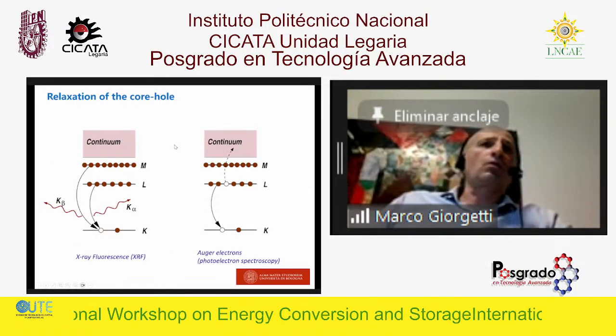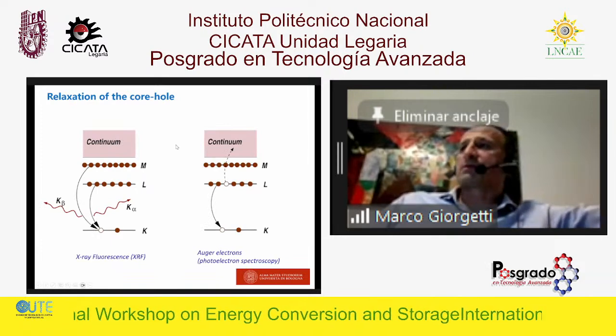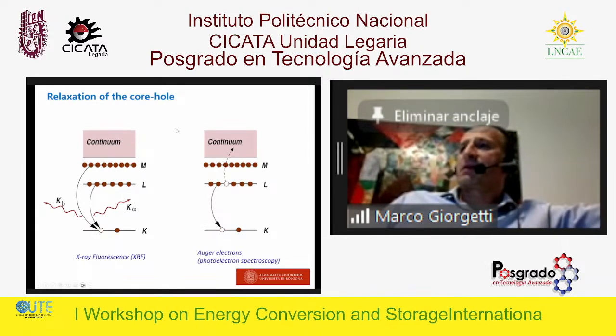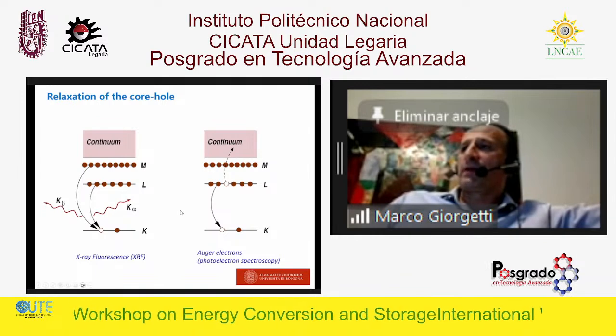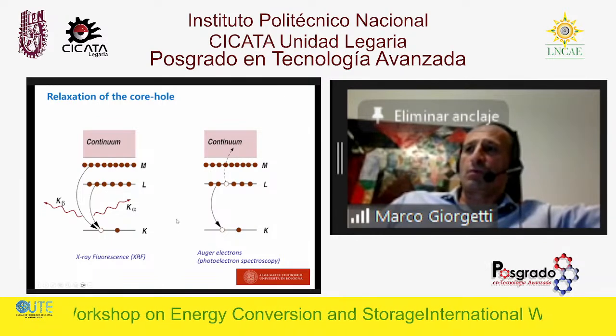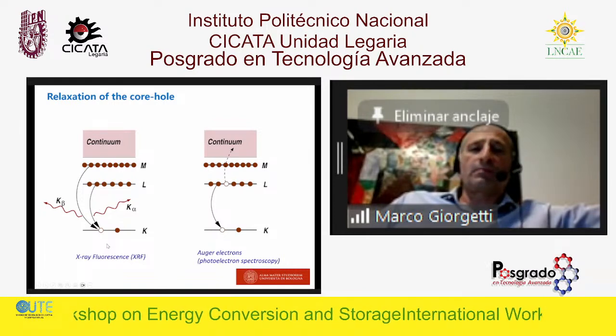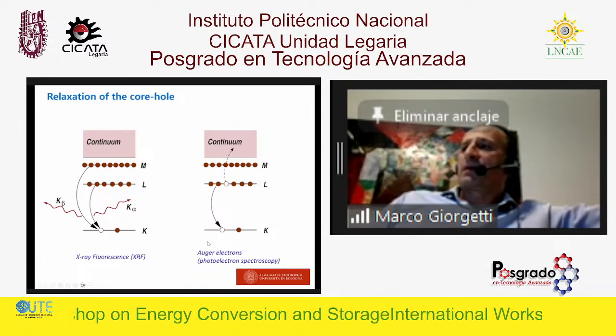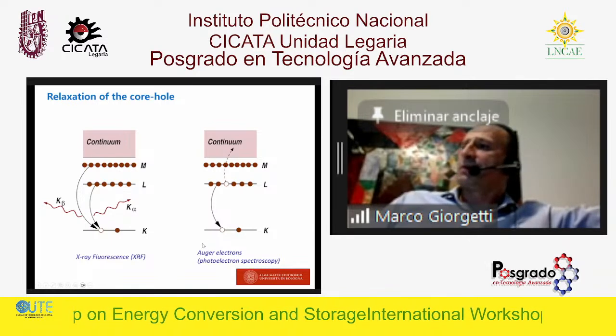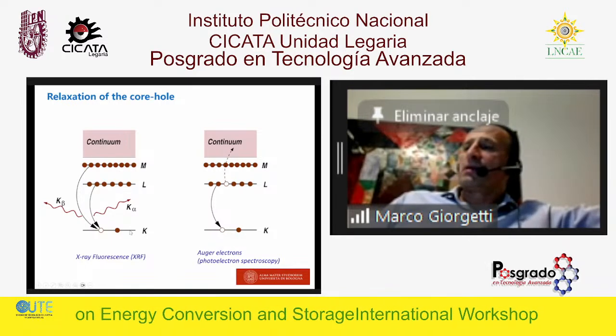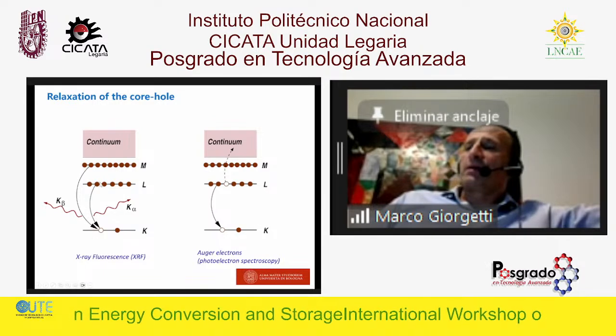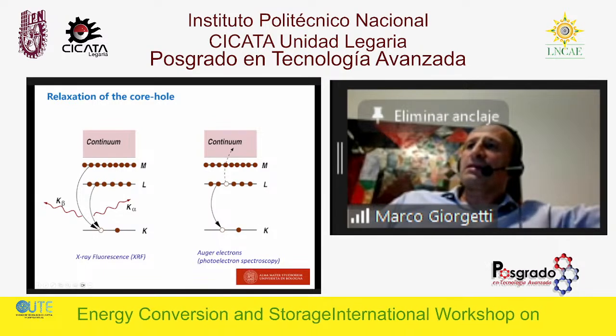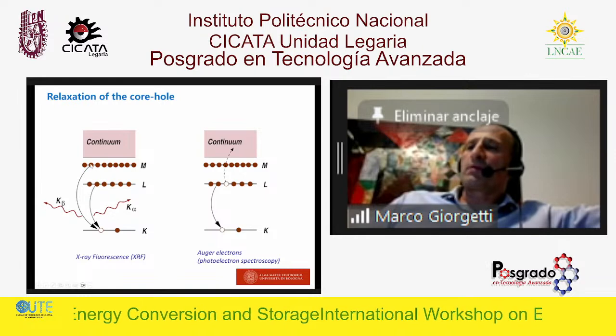when you create the core hole, of course, the process is very unstable. So we have a couple of very interesting phenomena that you also know well. One is X-ray fluorescence, because this atom is very unstable. And the other is the Auger effect, named after the French scientist who first observed the phenomenon, so they are called Auger electrons. Basically, here this vacancy is filled by some electrons from above.